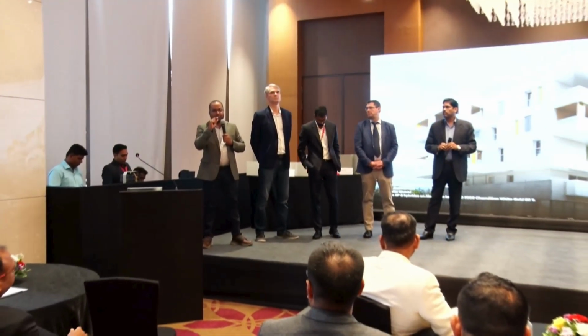In AZ, one property that has been educated in the market is that because it's aluminum, the light gets reflected, and because of it, 5 degrees of temperature gets reduced inside the building. So is this the same case with ZM, or are we wrongly educated? No, it's gloss management. Eventually it doesn't come from that. One thing you have to know: when you buy a color coating, it comes after galvanizing. So aluminum underneath the color cannot give that kind of reflection, unless you use bare galva. But how much bare galva do we use for buildings?